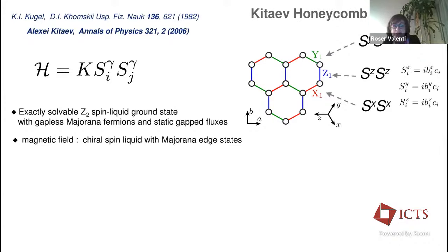The genesis of this field started with a very simple model from the first point of view, which is a nearest neighbor Ising model, which is bond dependent on a honeycomb lattice. If one thinks about the properties of the system, this is a highly frustrated model Hamiltonian, since if you consider, for instance, the spin here at the center of this honeycomb lattice, this spin has to interact with the Z component with the neighbors up in the lattice, then interact with the X spin component on the right, and with the Y spin component on the left. And since the three spin components don't commute with each other, this is a highly frustrated model.